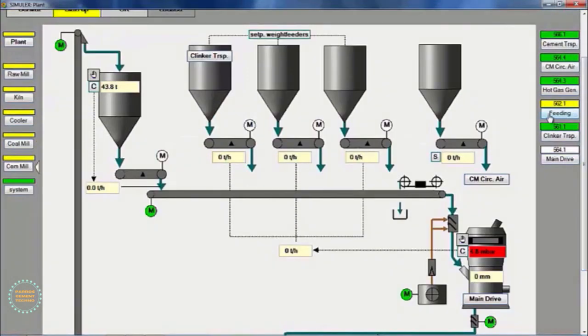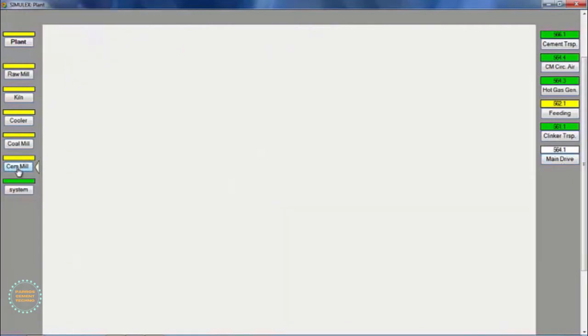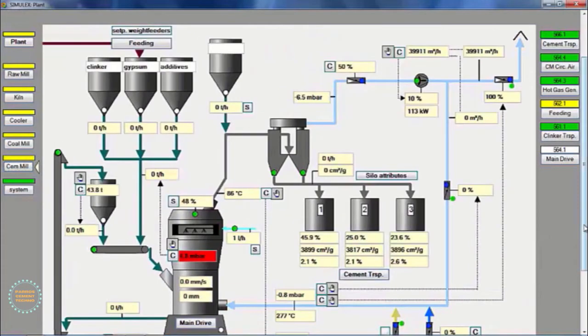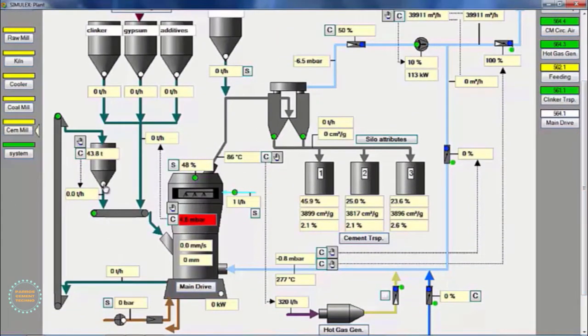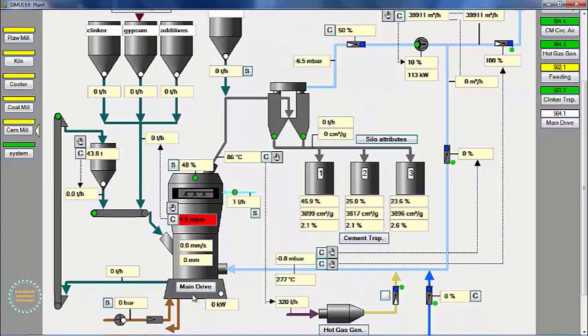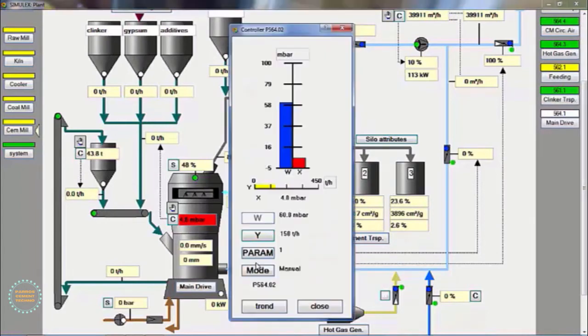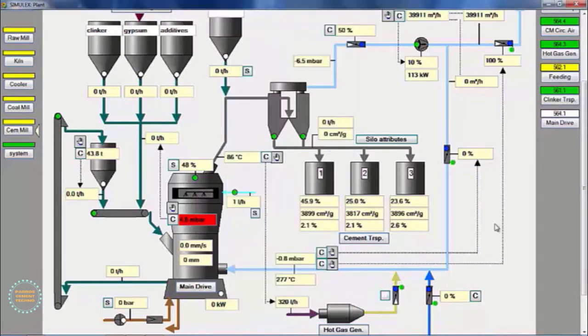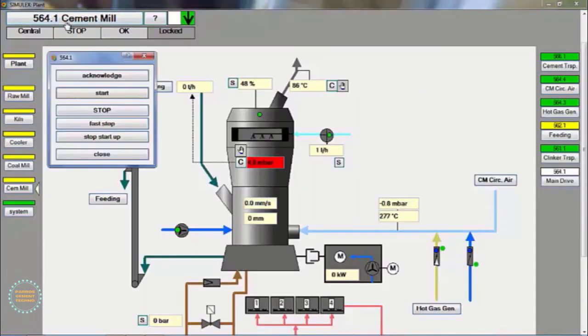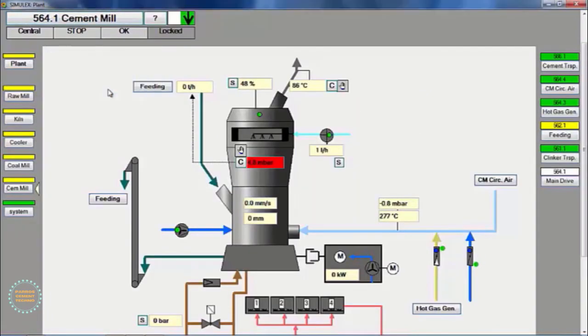In this simulation to start mill drive, there is no selection of roller-up mode and grinding mode. Before starting the mill drive, set the feeding setting between 30 to 50% of the VRM capacity, because when the mill drive starts, the material feeding starts automatically.